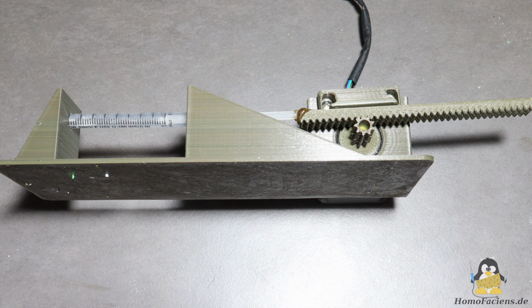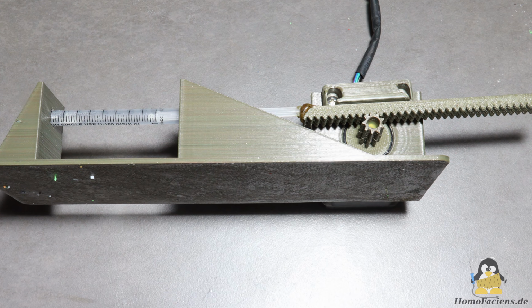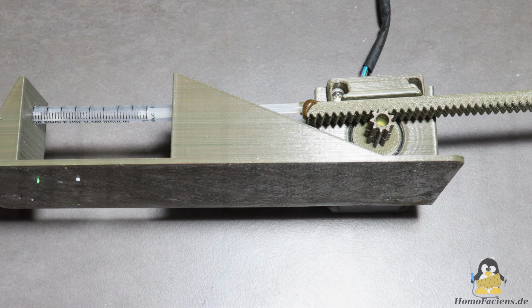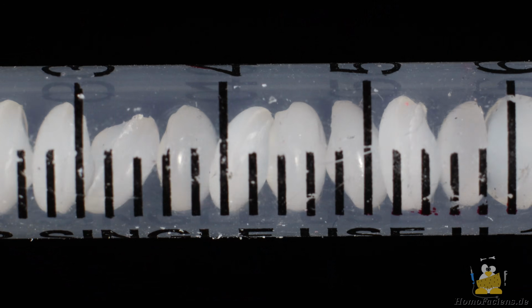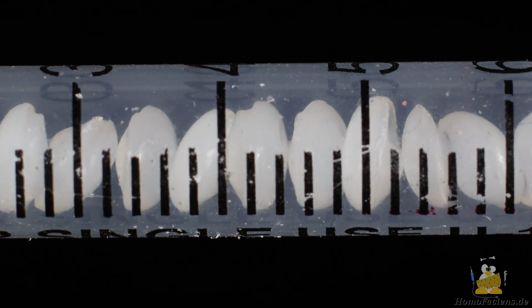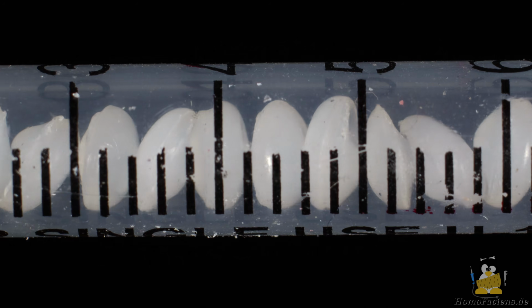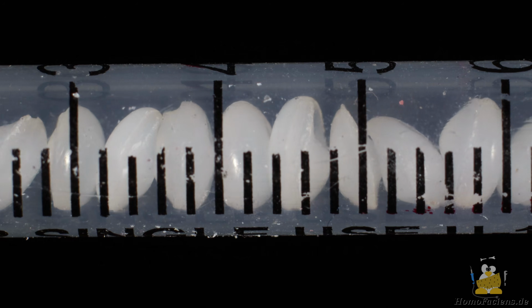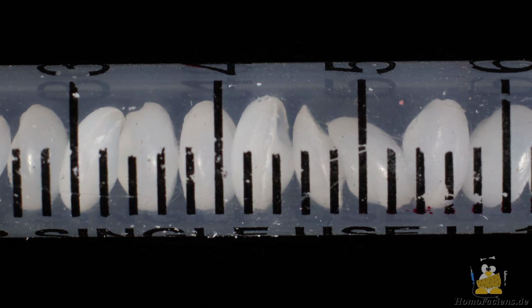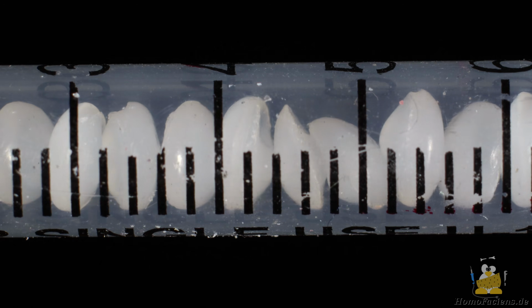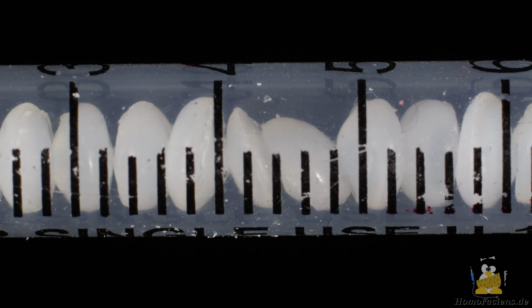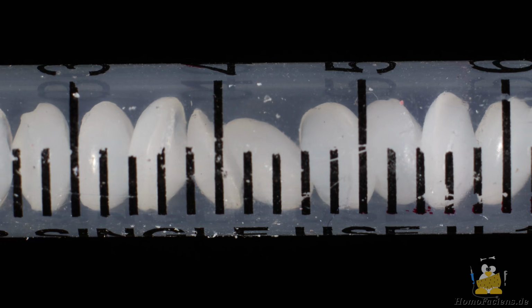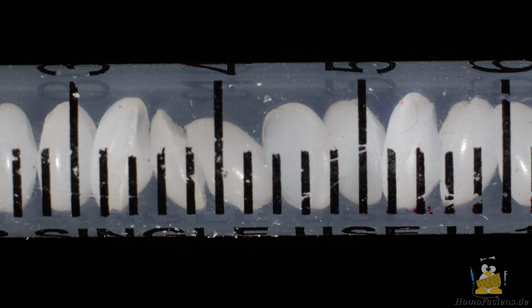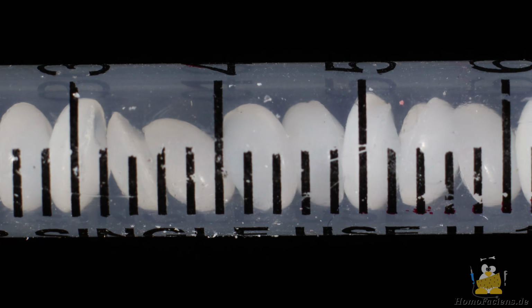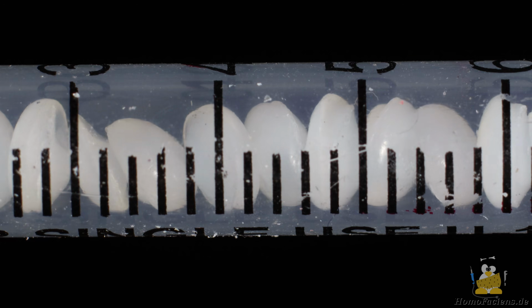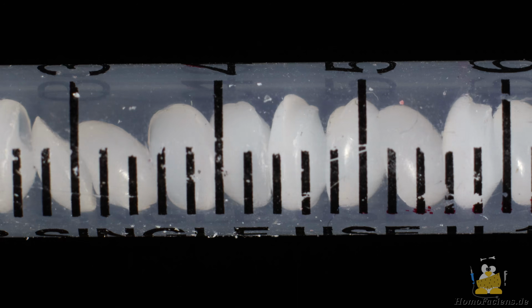For the next experiment I actuate the syringe piston with a stepper motor via a rack and pinion. The granules are slowly forced out of the syringe to the left. The movement of the particles is not uniform. It can be seen that the granules occasionally snag on the tube wall, causing the grains to be forced more tightly against one another. When the tension is released, a wave travels through the tube and the grains redistribute somewhat more loosely within the available volume.